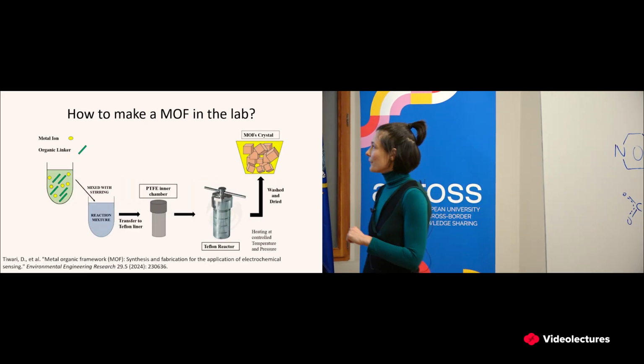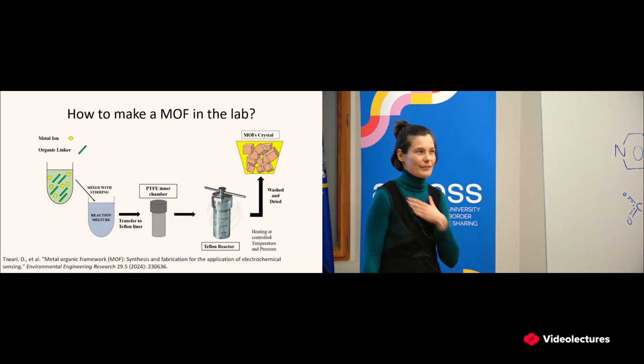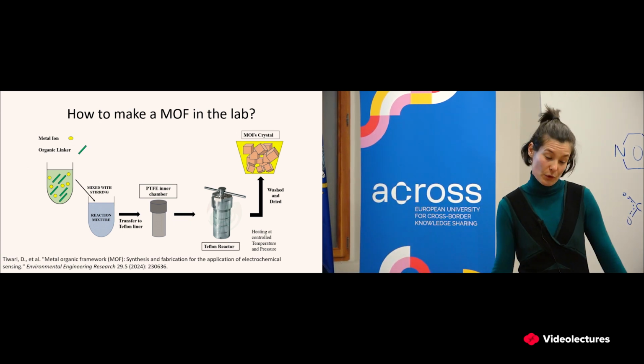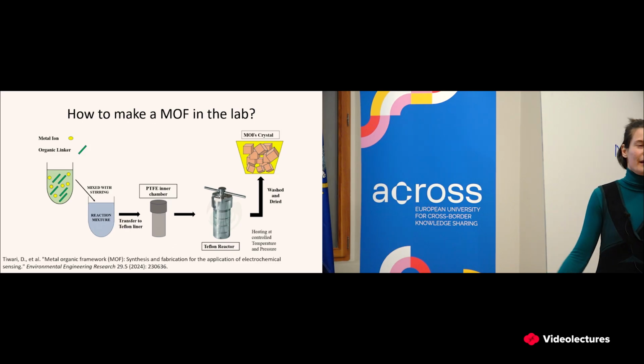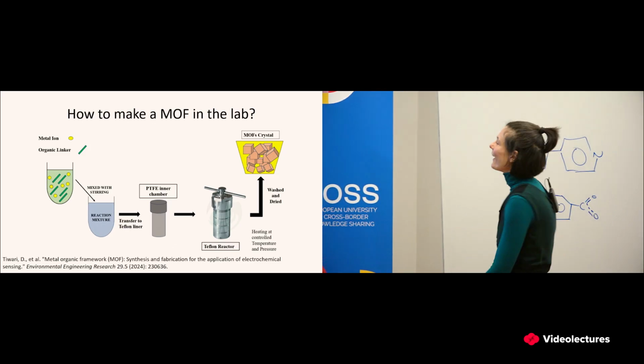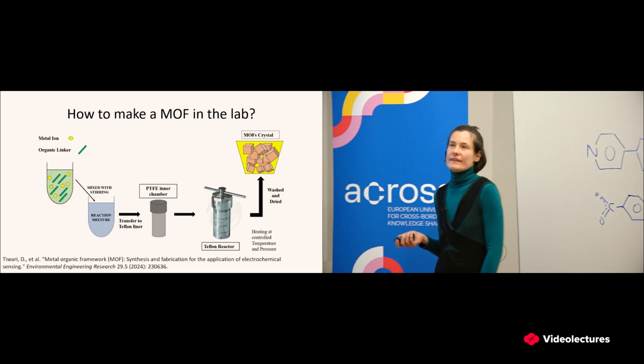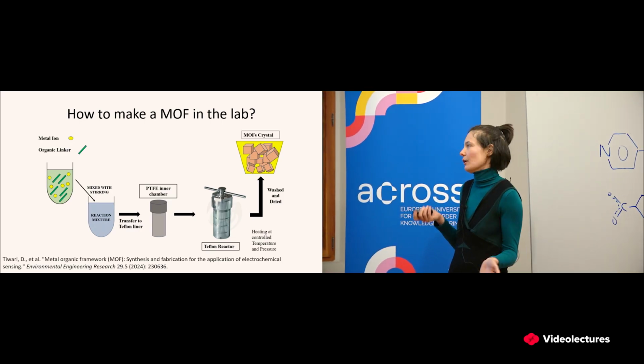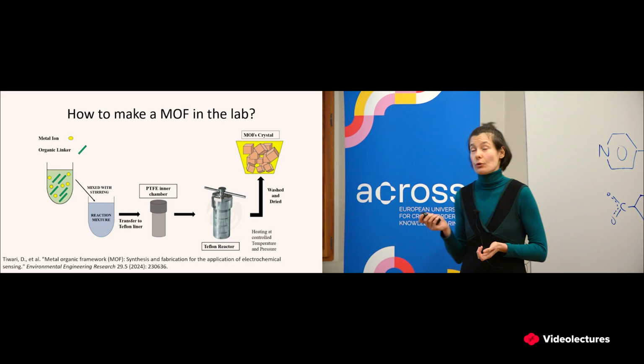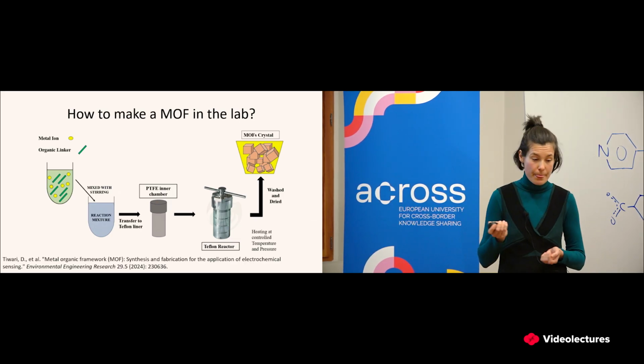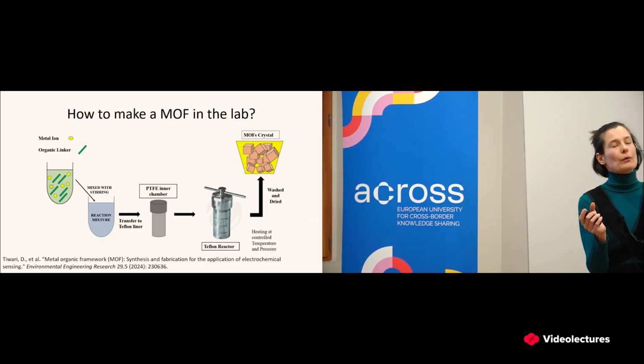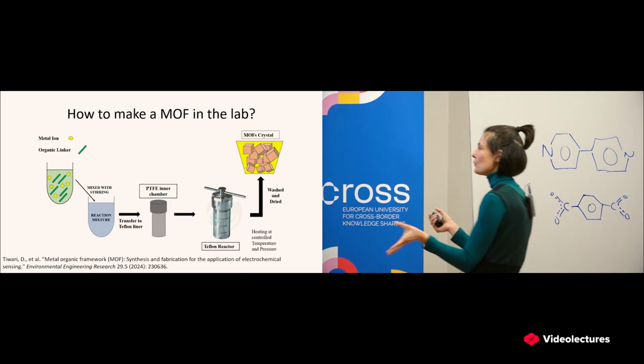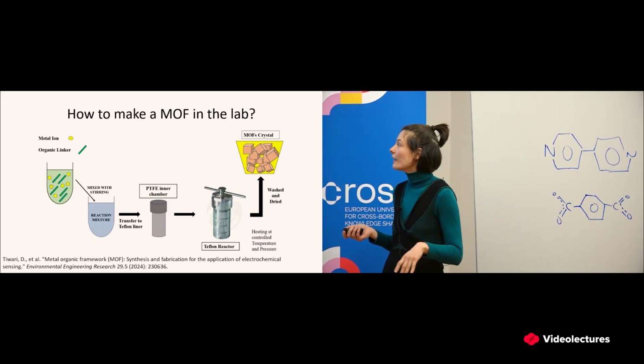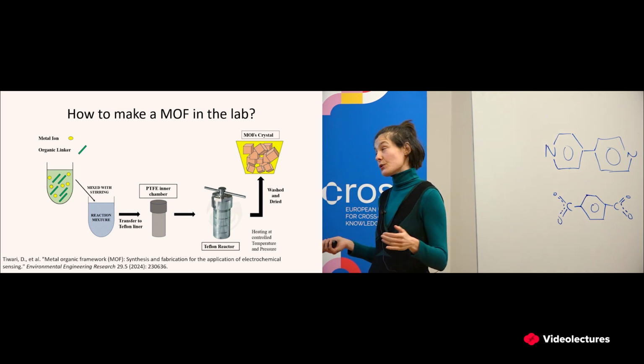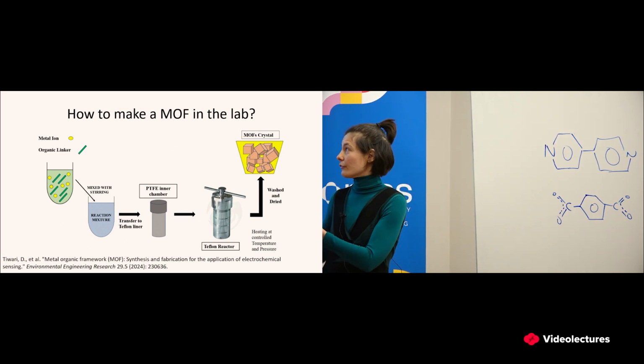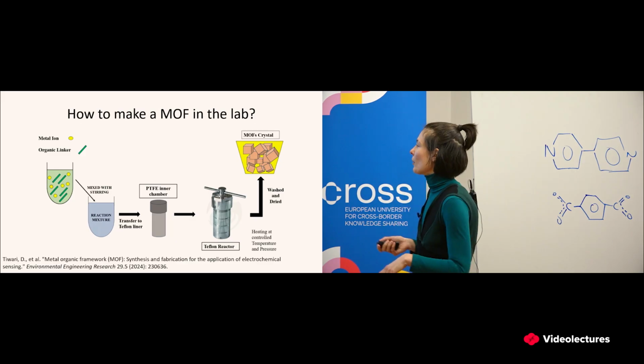Okay, so now let's say that you have felt somewhat inspired by this story and you are eager to go to the lab and make a metal organic framework by yourself. What do you need? This is roughly one of the protocols that you could follow. So you would certainly need some metal salts and some organic linkers. These are the two main components of a MOF. And you would have to stir these in some solvent. So you have to be careful which solvent you choose, because if one or the other of the two components doesn't dissolve, you will have trouble.